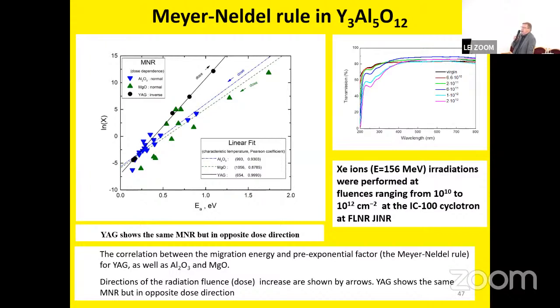In the case of binary oxides, activation energy goes down when we increase fluence, but for complex oxides like YAG or like spinel, activation energy goes higher when we increase fluence. And this is quite important because then we can predict radiation stability and radiation behavior for complex oxides where activation energy is higher after, let's say, strong radiation. This is quite a good point.